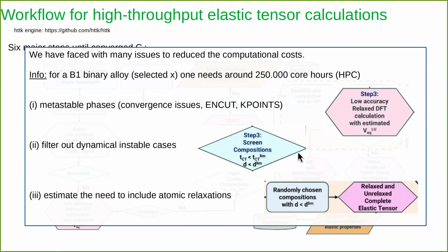One is that one can start with a really low accuracy, unrelaxed calculation. That means that we take low accuracy. In VASP, for example, we reduce the number of plane waves, and we take a really small K-max and so on, to get a feeling about how much computational time we need, or whether it will even converge or not. And after that, if it converges in a certain time, then we have the equilibrium volume, and at that point we can do a relaxed calculation, so we allow the atoms to move and relax and find their positions.